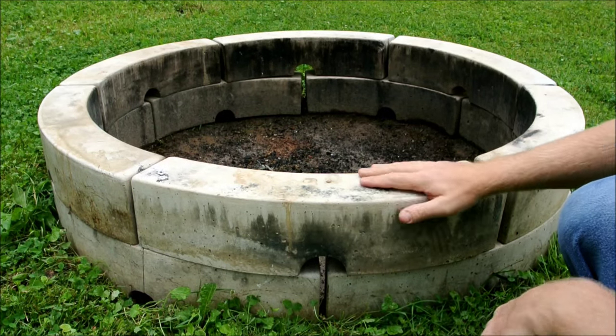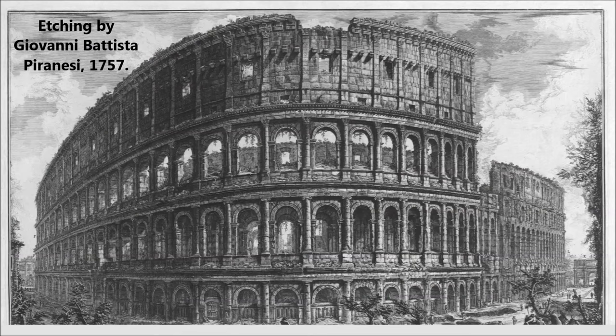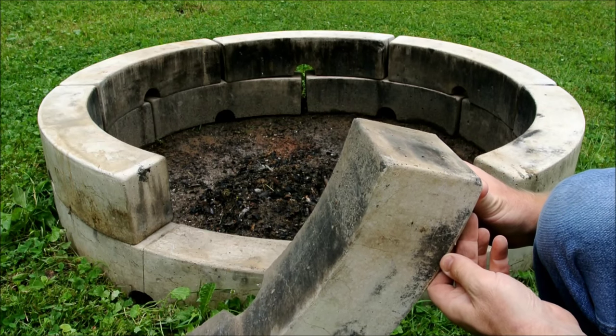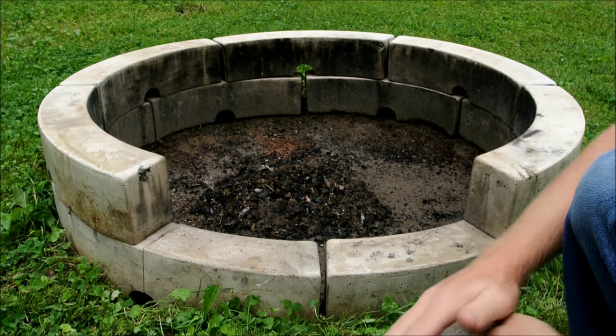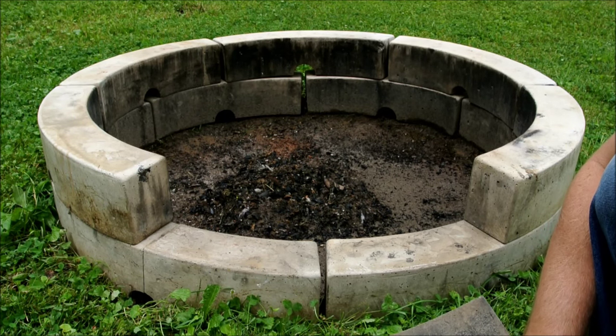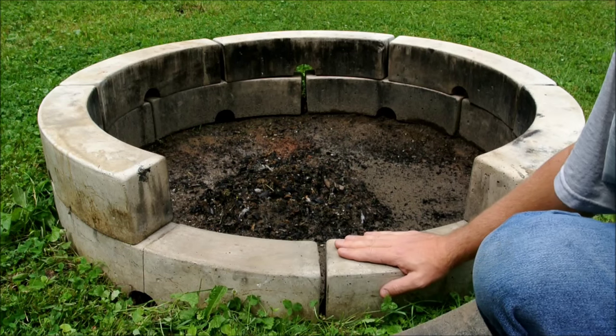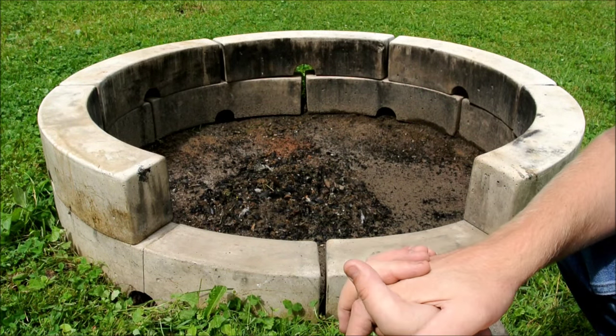Especially if people are just standing on one side, it projects the heat in that direction from against the back wall. I don't want to sound like the pretentious artist, but its design was modeled a bit after the Colosseum — that was the look I was going for. Each piece is 44 pounds, cast from refractory cement. I designed the part, made the mold, and cast it, then fired it to — I can't remember for certain — but I think it was fired to 1500 degrees Fahrenheit over 8 to 10 hours in the furnace.